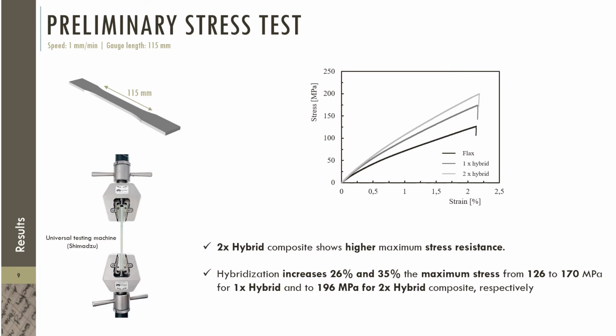The stress-strain curve of the tensile tests shows us that 2-time hybrid composites present higher maximum stress resistance. The hybridization also increased the maximum stress by 26 and 35% for the 1-time hybrid and 2-time hybrid composite respectively.